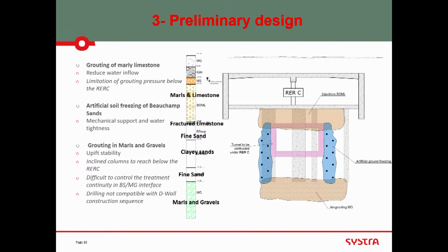The initial solution was kind of simple, but very difficult to put in place. It was, first of all, grouting below the slab of this area, the metro existing line. So grouting 2 meters below a slab, you don't put pressure. If you don't put pressure, you don't grout. So the result is difficult.